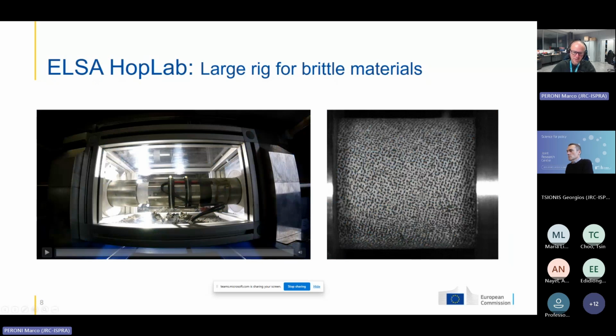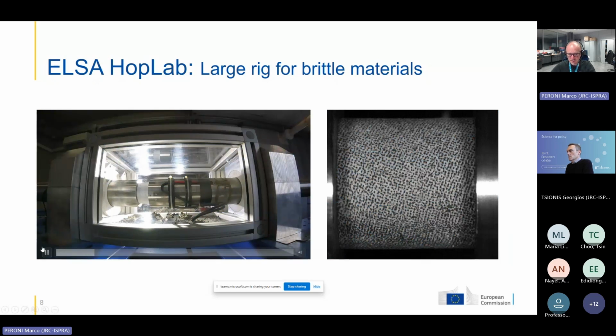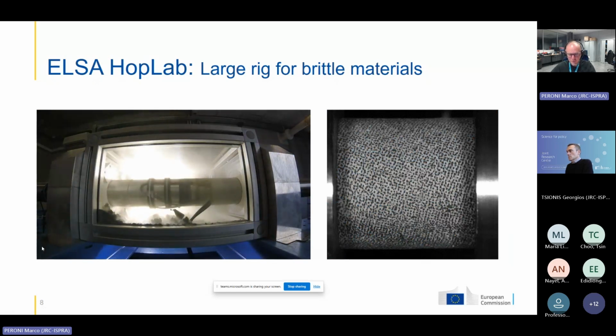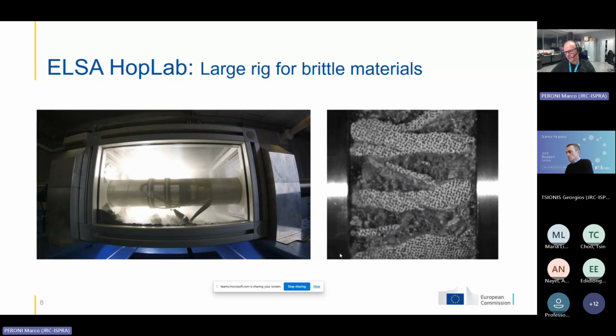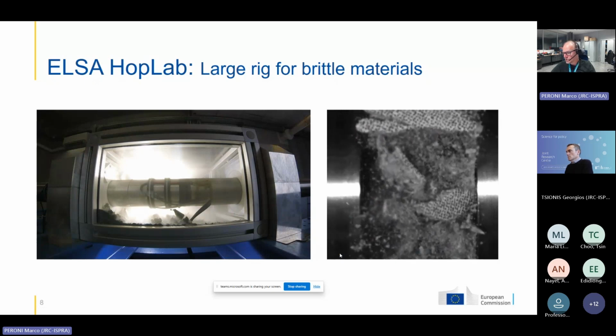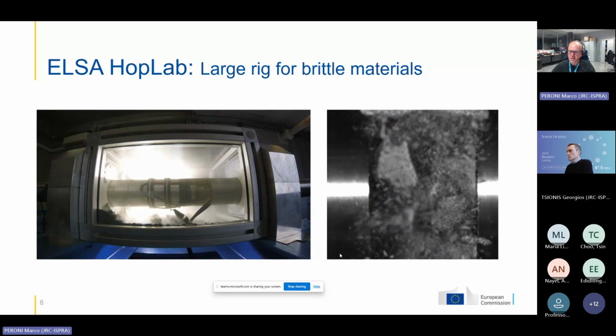You can see here the specimen on the left, this cylinder of 10 centimeters of diameter and 5 centimeters of length. This is a video at real velocity. You see that practically the test lasts very few instants, and with your eyes it's not possible to see practically anything. But on the right, you have a high-speed recording, and you can see that it is feasible also to apply digital image correlation or to track the movement of the machine during this kind of phenomena that lasts less than 1 millisecond, sorry.